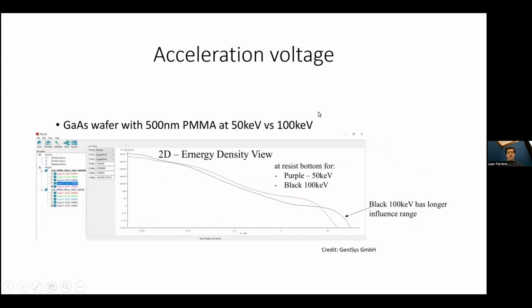And this is showing the same plot, but as a two-dimensional energy density. You can see the forward scatter. The purple is the 50 kilo electron volt, so it would be this. It's a little less sharp in the forward scatter regime, but you have less back scattering. And similarly, at 100 kilo electron volts, the forward scattering part is sharper, but you get more back scattering.